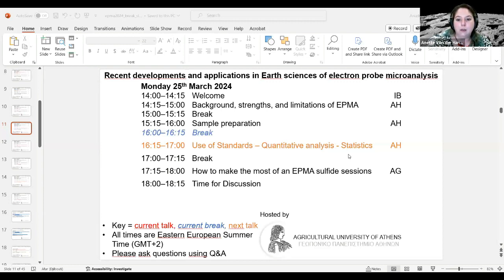if you have to buy new ones, it's worthwhile to check online, or ask, or check the Edinburgh website if it's known to have high amounts of a certain element that may interest you. And if you already have the epoxy and you're worried about it, just analyze it, again not with a focused beam. We usually try to avoid analyzing epoxy, but if you do it gently with a widened beam, it doesn't vomit into your sample chamber and you still get some analysis, and that gives you information. Same if you're interested in CL: there are resins that have more CL than zircons or apatites, and that can be a real problem when you're interested in that aspect. Likewise, there are other ones that are very low. So before you mount all your stuff in the wrong type of resin, making an empty epoxy mount and having a look is useful.